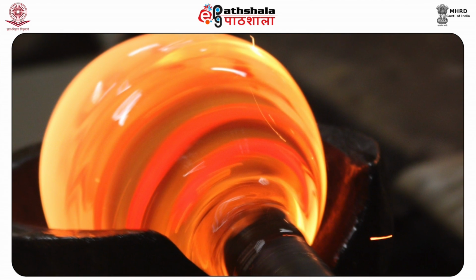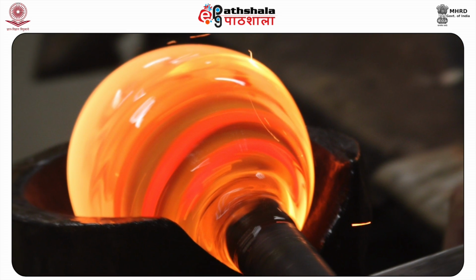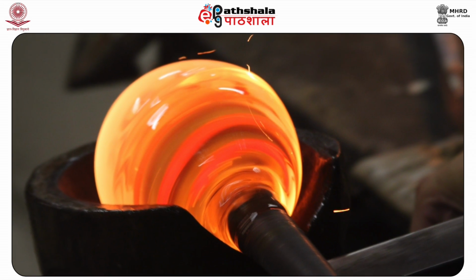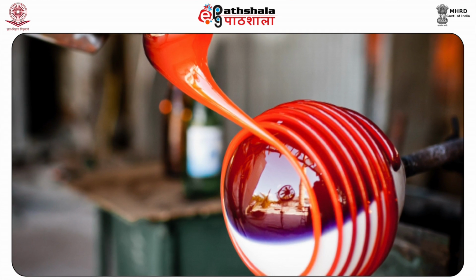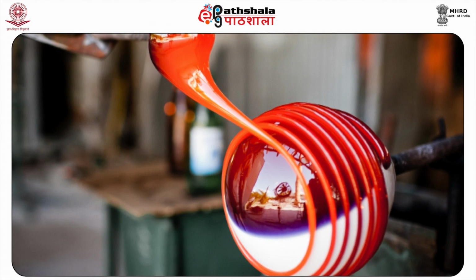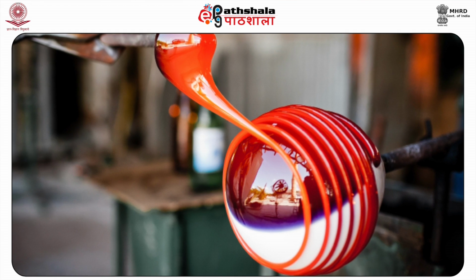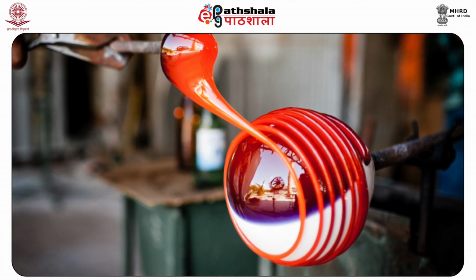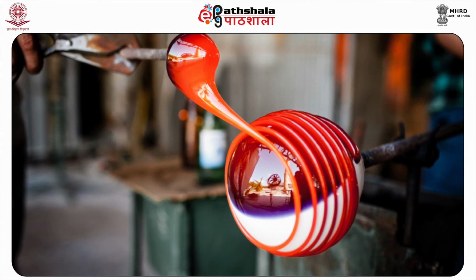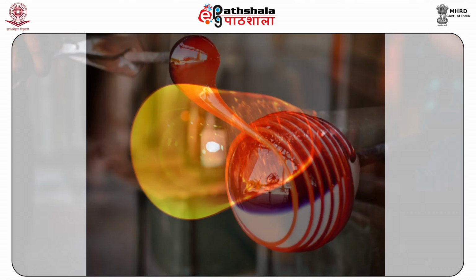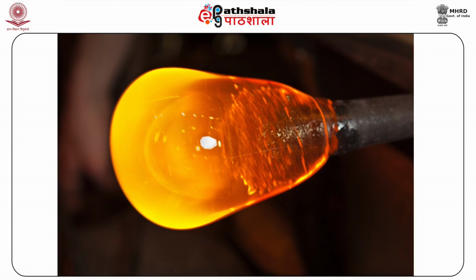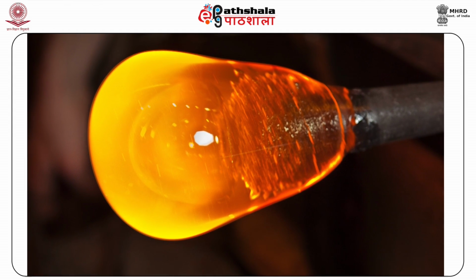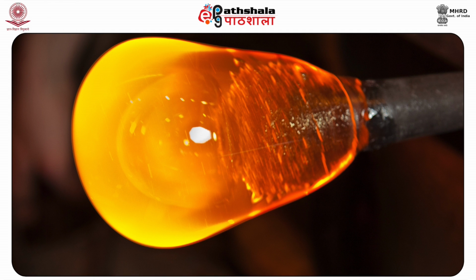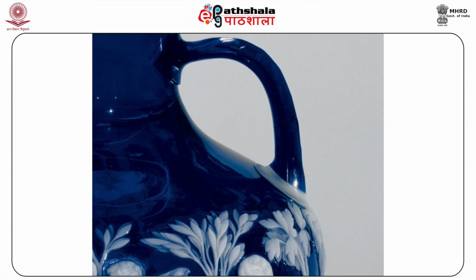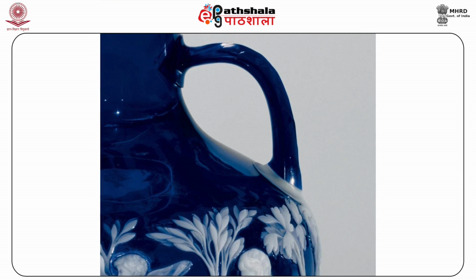The process of free blowing involves blowing short puffs of air into a molten portion of glass called a gather. This is coiled at one end of the blowpipe, with the consequence of making an elastic skin on the inside of the glass blob that matches the external skin produced by the exposure to heat from the furnace. The glass worker then inflates the molten glass to a coherent blob and works it into a desired shape. One example of this technique is the Portland vase, which is a cameo manufactured during the Roman period.